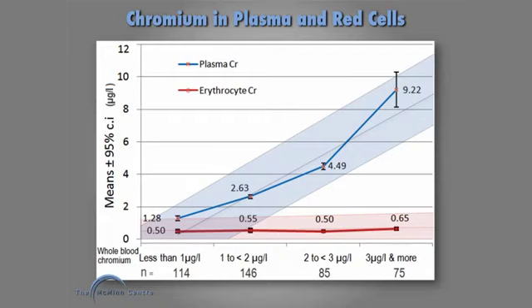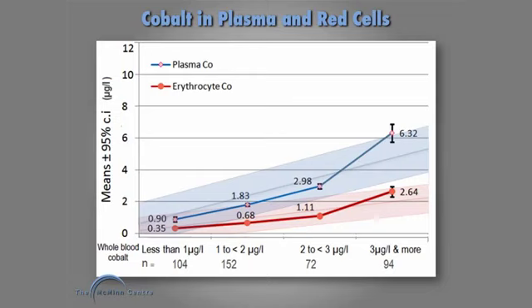So that is just evidence that the chromium generated from metal-metal joints is indeed chromium-3, and it does not enter the red cells. When you look at cobalt, however, the right opposite is the case. And again, we've got the same groups. And as the plasma cobalt level goes up, the red cell cobalt also increases. So cobalt enters cells, chromium-3 does not, chromium-6 does, like cobalt, enter cells.